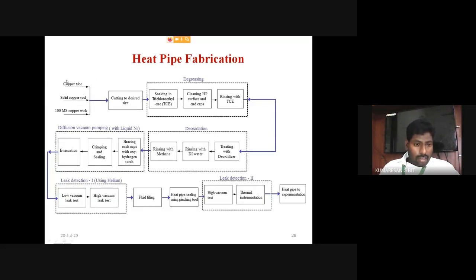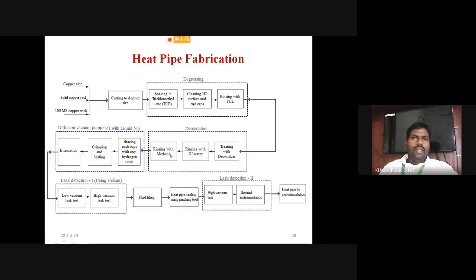Then these components are taken for the degreasing process to clean the heat pipe. Then this is taken for the deoxidation process, because once we fill the copper tube and the ends are sealed, we don't have the provision to open and clean the heat pipe frequently. So that's why the deoxidation process is taken initially. Then it is treated with the deoxidizer, and these materials are mixed with the methanol fluid. Then it is kept for 1 or 2 days for the deoxidation process.